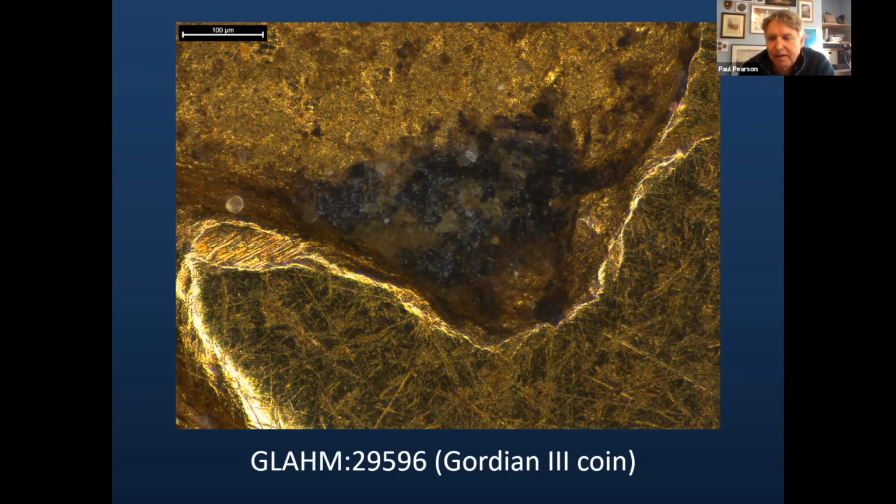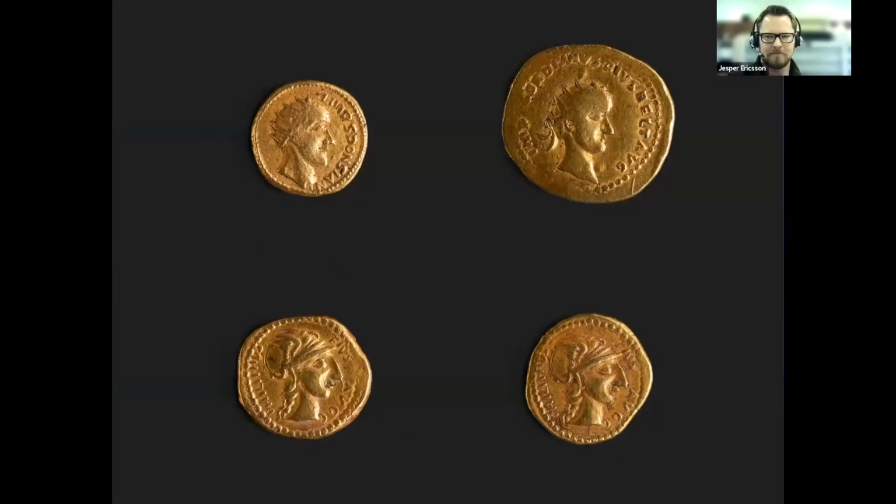We compared that again with known genuine coins, and the appearances are exactly the same. It's quite technical, and there's lots of discussion, but the bottom line is our work established to our satisfaction, beyond any reasonable doubt, that these coins were buried for a very long period of time before they appeared in 1713, because they've been in museum drawers since, and that burial happened after they acquired their highly worn surfaces. So, summary: after all this analysis and the results, we feel that we have authenticated the coins as being products of antiquity and not fakes.